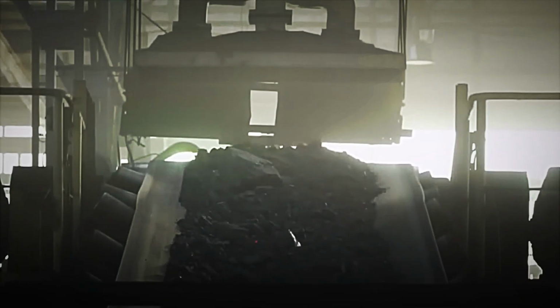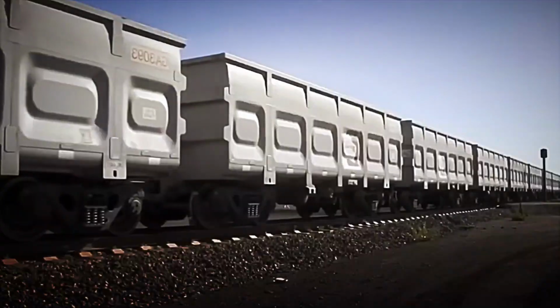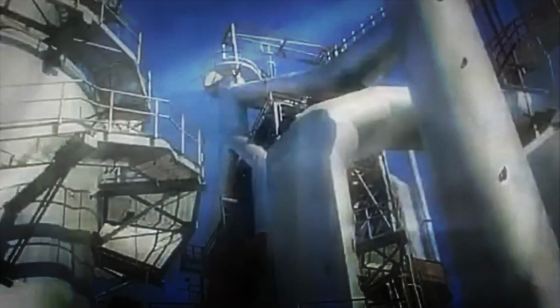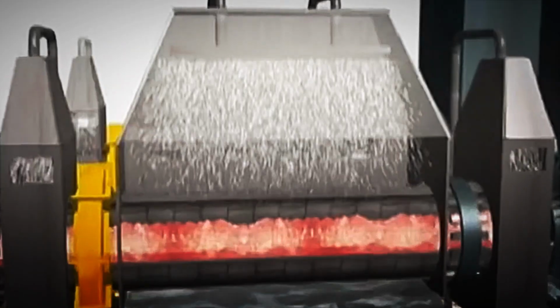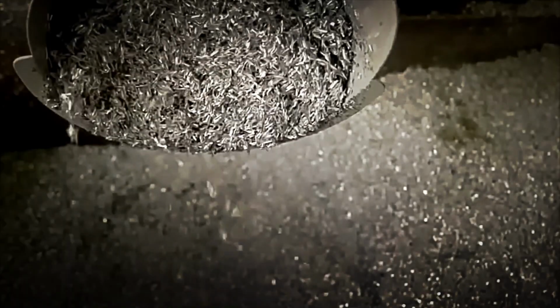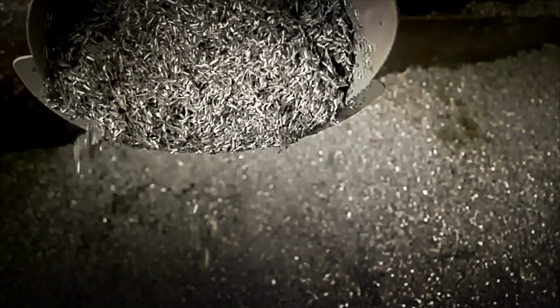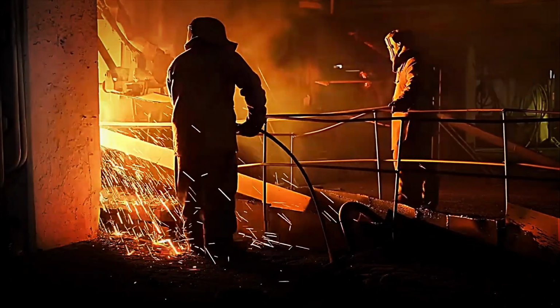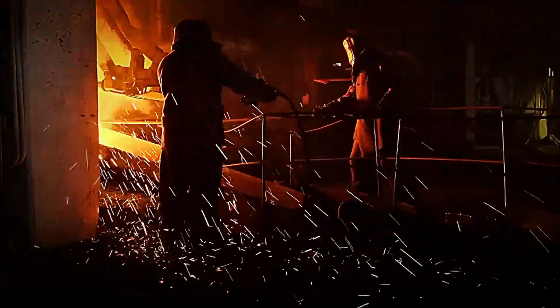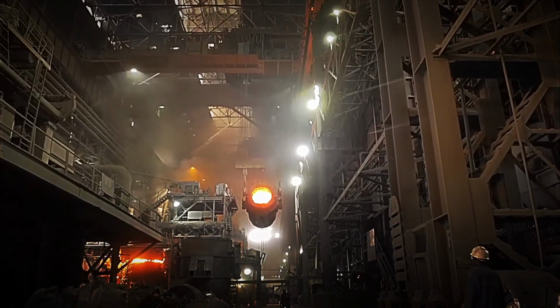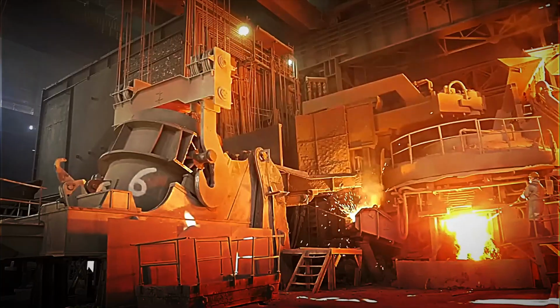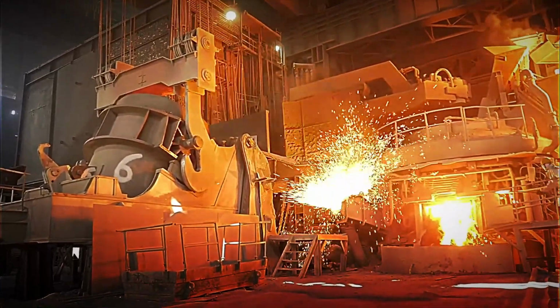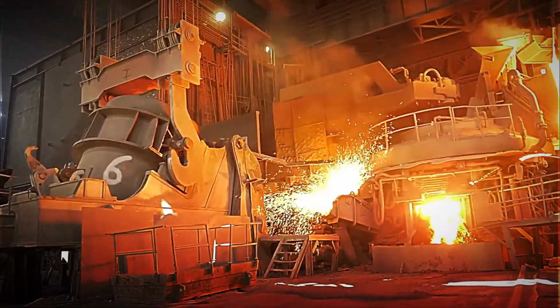The furnace's operation combines chemistry and engineering. Iron pellets are loaded from the top, along with coke, a coal treated at high temperatures, and limestone. Preheated air at over 1,000 degrees Celsius is injected from the base. The coke burns violently, generating carbon monoxide, a gas that separates oxygen from the iron ore. This process is called reduction. The oxygen is released as a gas, leaving the metallic iron behind.